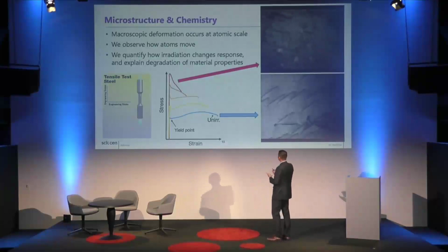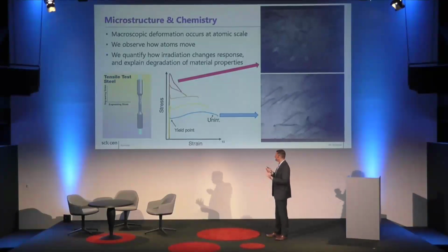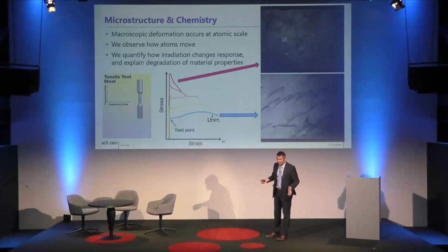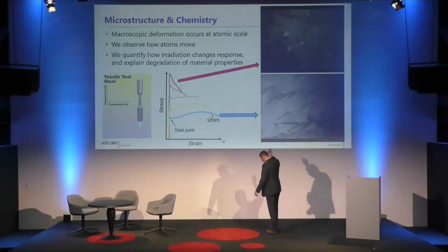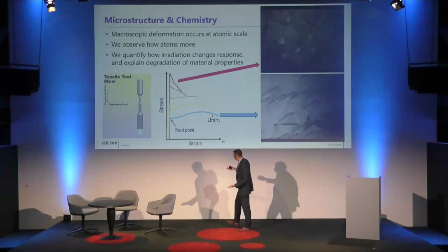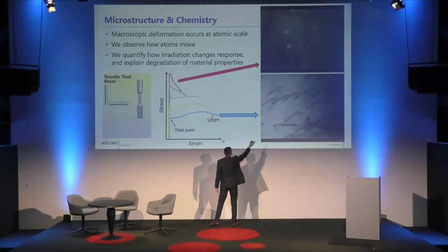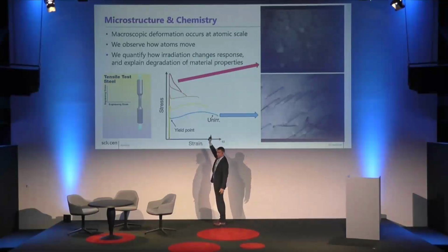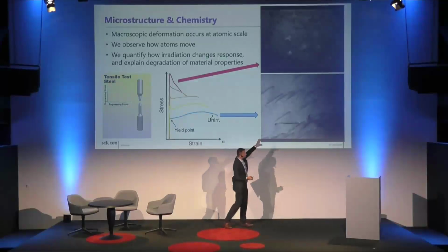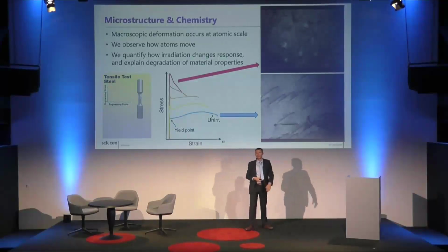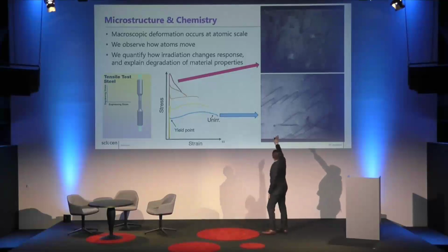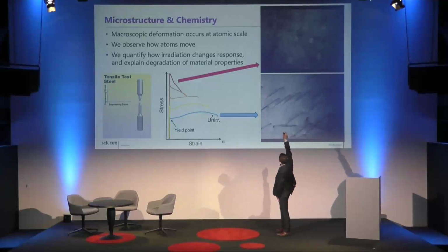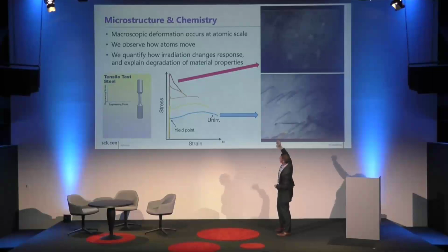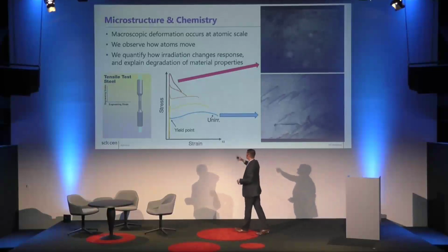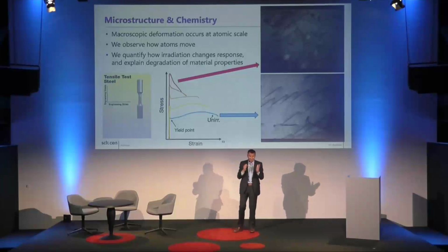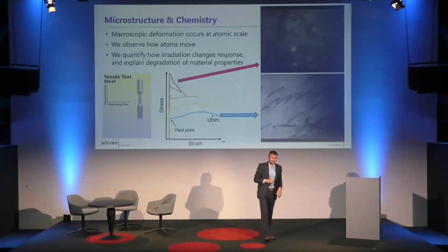Then for the microstructure, we are using the tools that allow us to see atoms. I mean, no wonder these days many people can see atoms. And here I just would like to give you an example of what it means to study microstructure. Here is the microstructural response of the material that is in non-irradiated state, in reference state, and you see dislocations. These are 1/2 <111> dislocations. It's a BCC iron. But if you irradiate it, for instance, with neutrons, you will have a damage pattern. These are the bubbles. And then dislocations are bending around those bubbles. And that explains why your material becomes brittle, when it's no longer ductile as before.